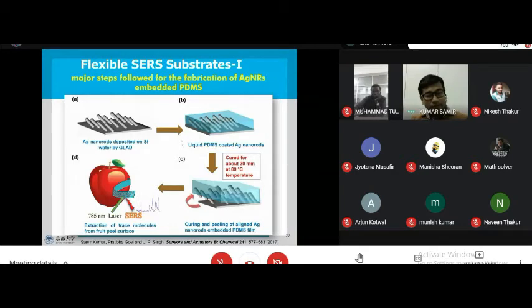So for fabricating this SERS substrate, first silver nanorods of around 1 micron length were deposited on a silicon wafer. Then liquid PDMS was poured on it, and it was cured for 30 minutes at 80 degrees, and we peeled it after 30 minutes. And then SERS measurements were done on this substrate.